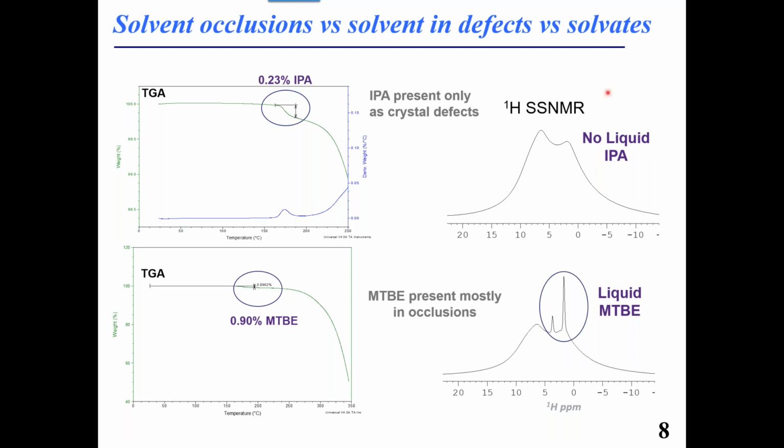Whereas if it was lattice bound, that's exactly what I mean by the solvate. That would be the remaining case that is not shown here. You wouldn't see the liquid in proton NMR, but you would see phase separated sets of peaks, including the solvent itself in carbon and or fluorine, nitrogen, and so on. So absolutely, it's one of the strengths of solid state NMR.